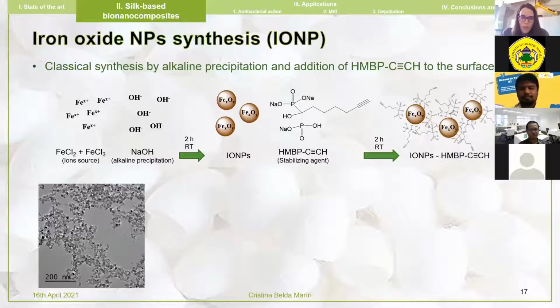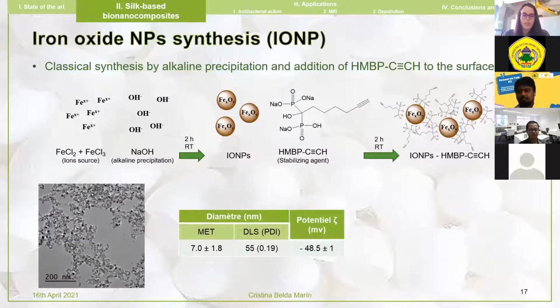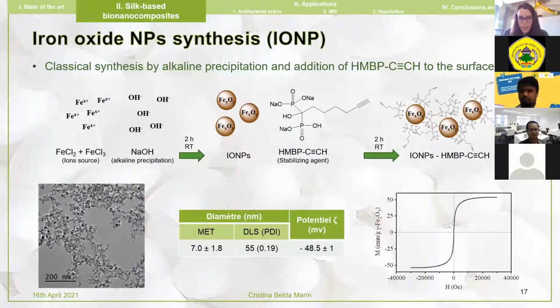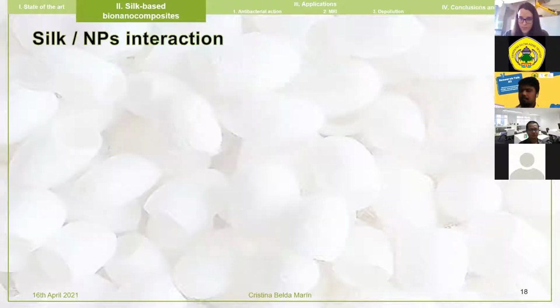So as you can see from the transmission electron microscopy image, those nanoparticles tend to aggregate much more than the other two, and that's easily explained because of their magnetic attraction. But still, we have rounded nanoparticles with a monodispersed size. And what's important about iron oxide nanoparticles is that they have this superparamagnetic behavior that allows, for example, their use for magnetic resonance imaging, as we will see later.